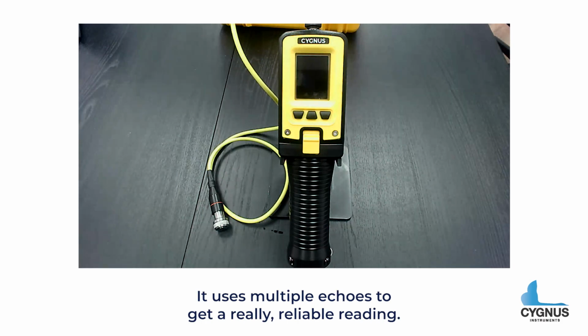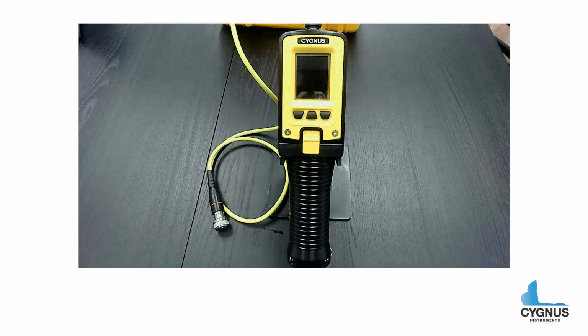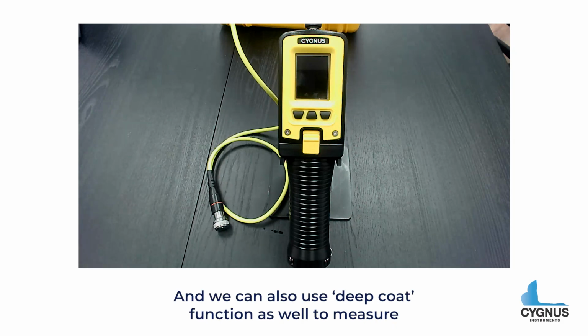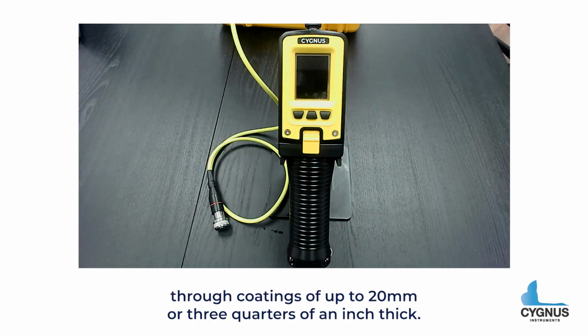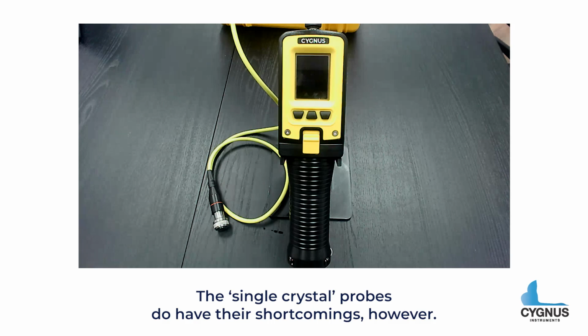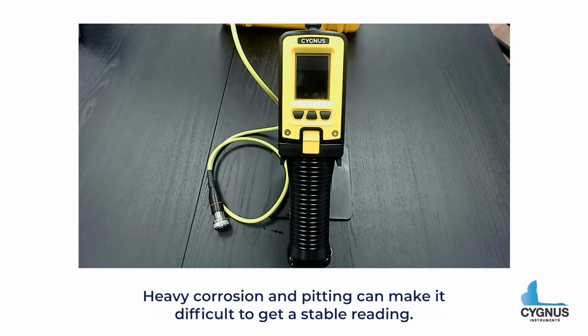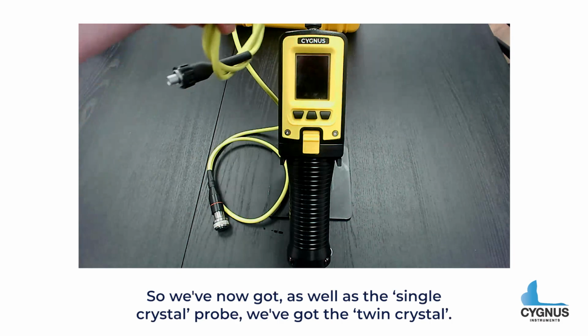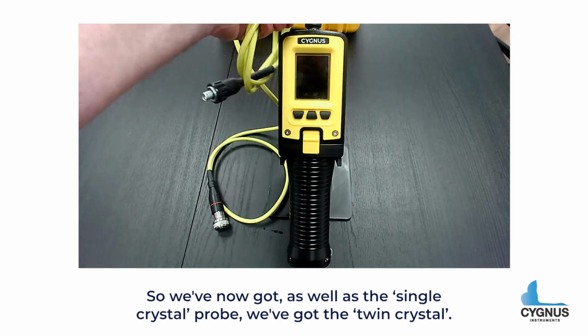It uses multiple echoes to get a really reliable reading, and we can also use the deep coat function to measure through coatings of up to 20 millimeters or 3/4 of an inch thick. The single crystal probes do have their shortcomings, however. Heavy corrosion and pitting can make it difficult to get a stable reading. So as well as the single crystal probe, we've now got the twin crystal.